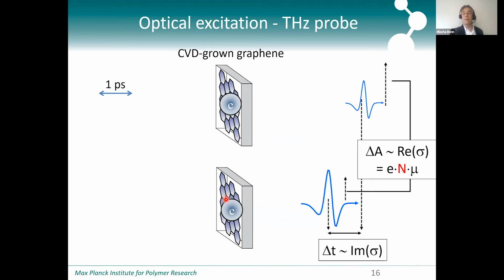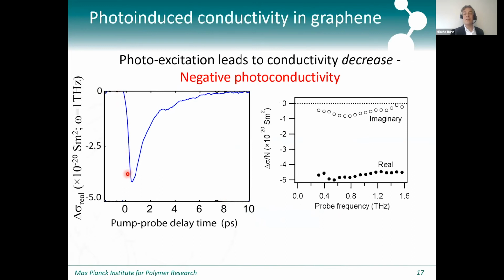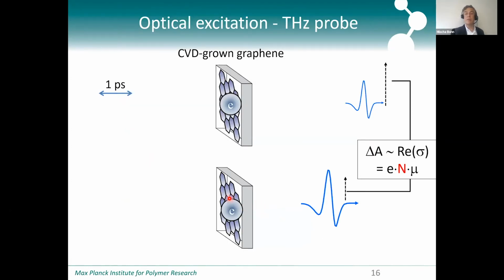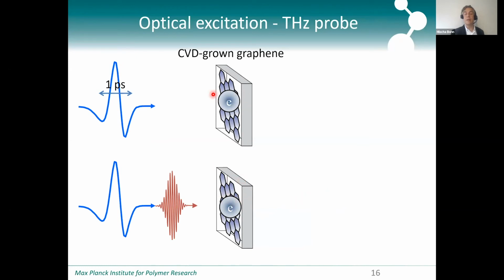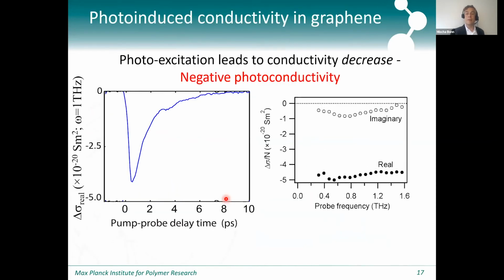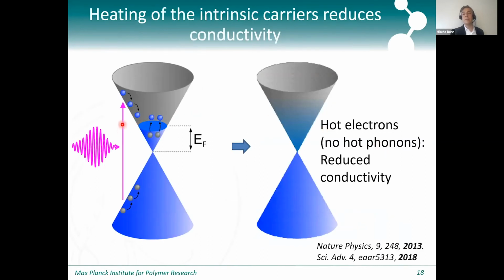And that increase in transmission corresponds to a negative photoconductivity. So that means that we had initially in our sample a photoconductivity here and here that was equal, and somehow the optical excitation has reduced the conductivity in this case here. And so the spectrum looks like this. The spectrum is actually not very informative, but we can understand this reduction in the conductivity quite nicely when we understand that the excited electrons will cool down through this Dirac cone here, and it will do so by scattering with other electrons that are present in this Dirac cone.